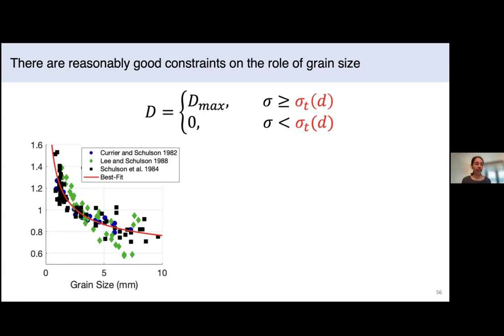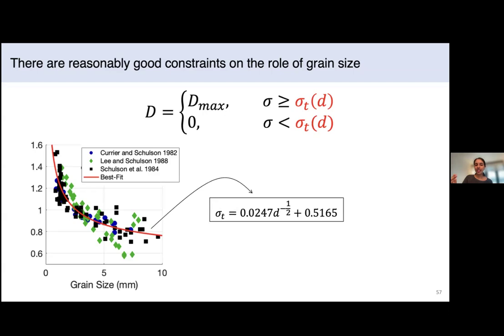There have been these three studies looking at how ice strength varies with grain size. And they find a pretty clear relationship that can be fit with the best fit line: ice strength is inversely proportional to grain size. As ice grains grow, you would expect ice strength to decrease. That could be due to a lot of physical processes, but it can be understood by that little theoretical exercise I did: if fractures are opening up along grain boundaries, as grains grow you get more grain boundary area, and therefore cracks could propagate even further.